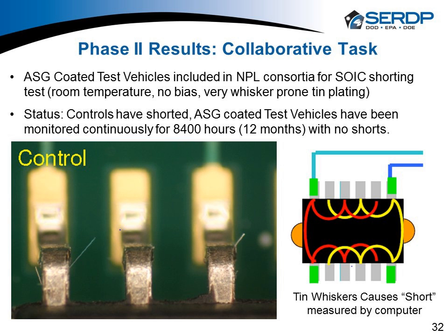And so they don't have to put them into a scanning electron microscope. They can just plug it into a computer and let the computer do all the monitoring. And so we were able to get a set of test vehicles, and they have their own test vehicle. It's got all these little SOIC components on it. There's 24 parts per test board. We have 2 test boards in their test. They put those in, and we've gone now 12 months, right around 8,400 hours with no shorting. Their controls shorted out in the first 2 weeks. So the liquid glass coating is performing very well in their test.